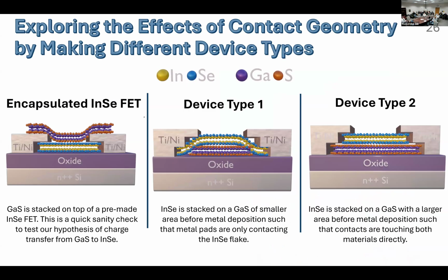So before I go on to talk about these 2D HEMTs, there's quite a few different device geometries that I'm going to introduce because I want to look at a couple of different things. As I mentioned earlier, I suspect that the gallium sulfide is going to introduce some electrons into the indium selenide as soon as I put it on top. So in order to check whether or not that is correct, I am going to use a pre-made indium selenide transistor and simply directly stack a gallium sulfide material on top. And I will measure the device properties before and after the stacking to see what the results are.